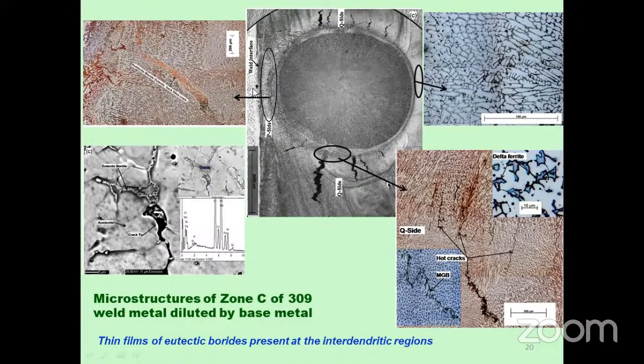Here there is a partially melted zone. Whatever liquid is formed here is backfilling the cracks that are formed near the weld interface. But these cracks which are slightly away from the weld interface, we can see that the cracks are open and very prominent. And when we did SEM analysis at this region, we found that there are thin films of eutectic present along the grain boundaries. These thin films are so fine that they are not sufficient to backfill these big cracks. So they are very fine and very flimsy. So these thin films of borides were present during our microstructural analysis.